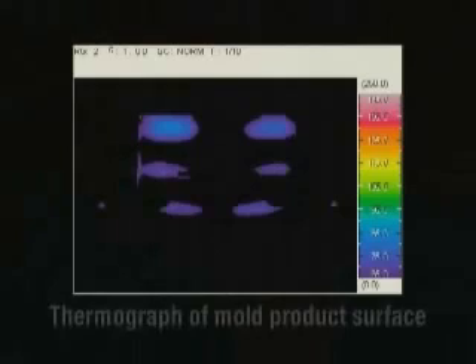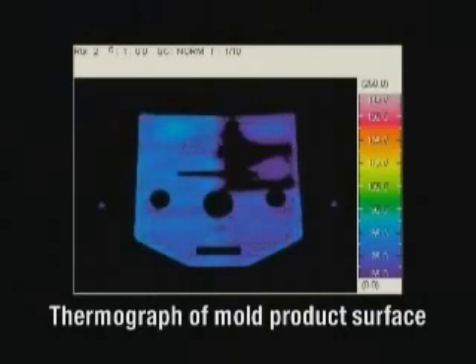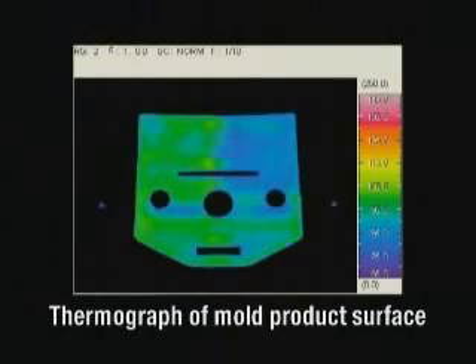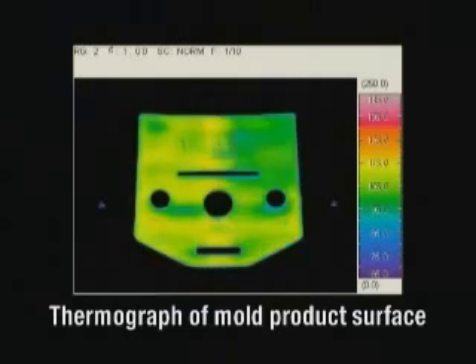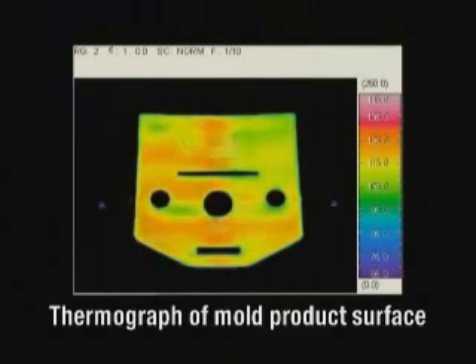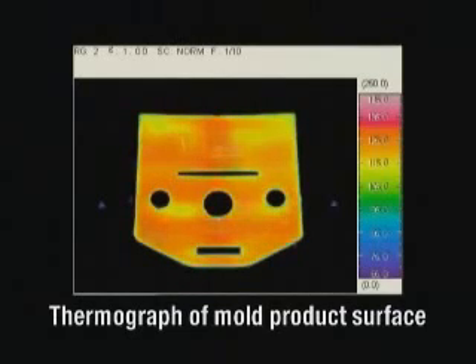Taking this automobile part as an example, it is now possible to raise the temperature at a rate of about 10 degrees centigrade per second. The time required to raise the temperature of the cavity surface from the 60 degrees centigrade mold temperature to 120 degrees centigrade is only 6 seconds.